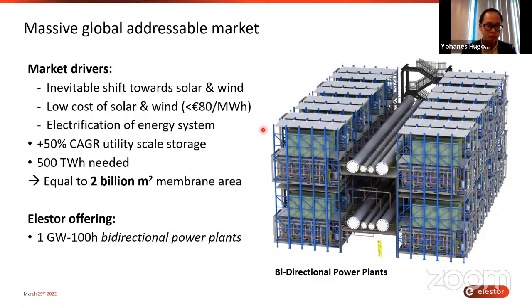Therefore, we see plus 50% CAGR for utility scale storage. It means the industry will grow more than 50% every year, until we reach a size of 500 terawatt hours. Currently, I think we are only at 1 or 2 gigawatt hours globally. If we are able to address this with flow battery technology, I estimate that we require at least 2 billion square meters of membrane area to fulfill this need. And this membrane also needs to be replaced once every 10 years, so it's also a very sustainable business.